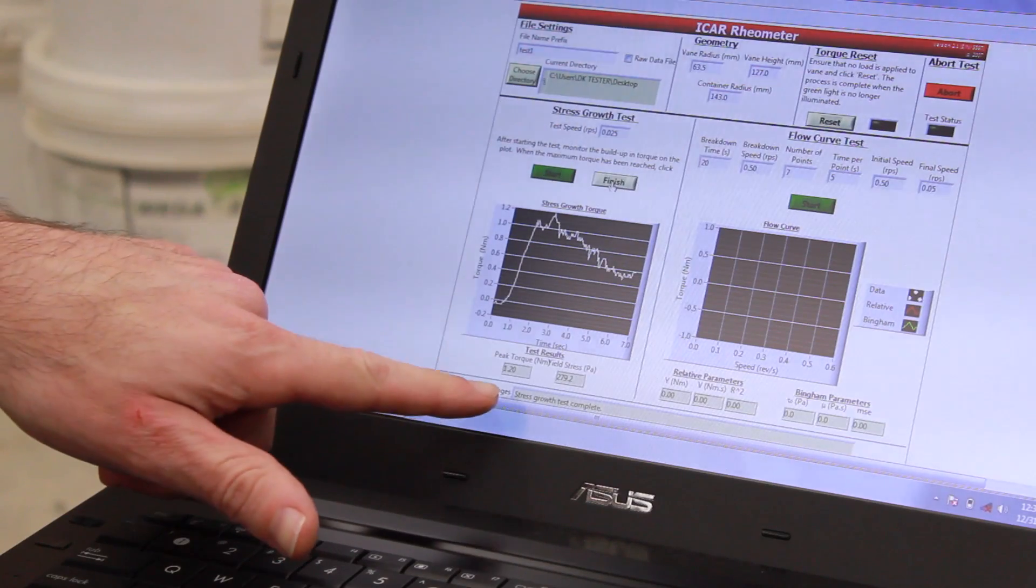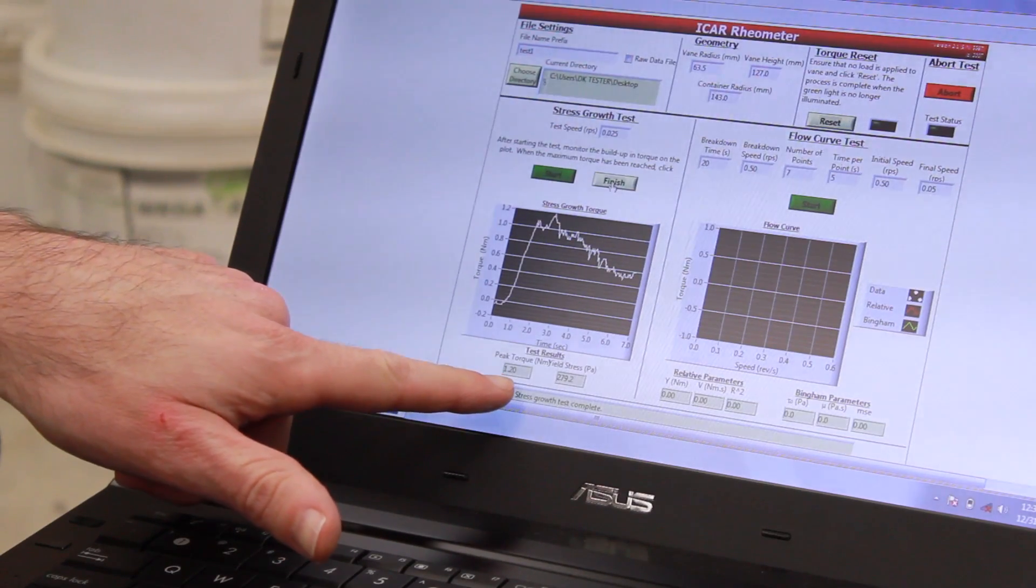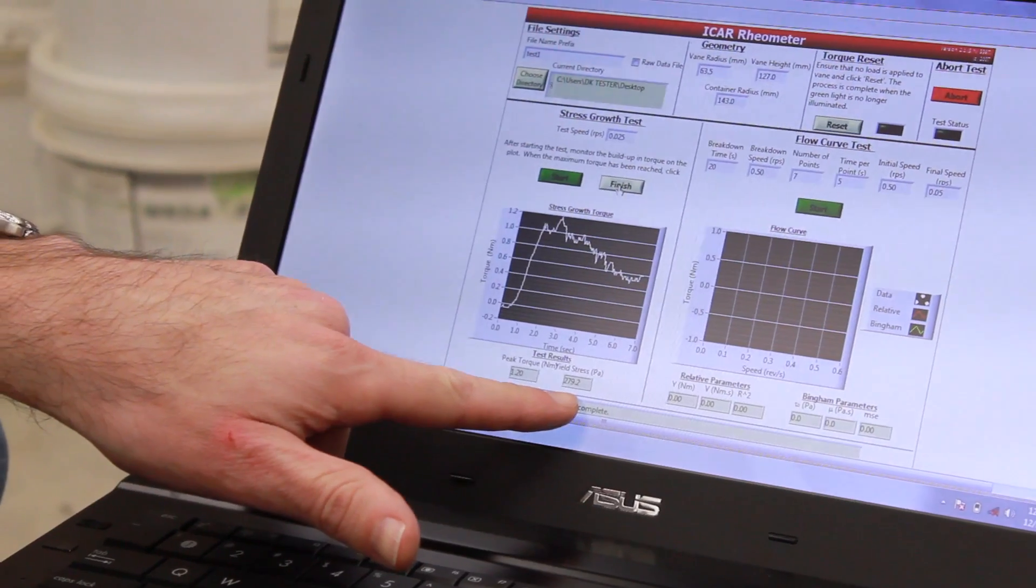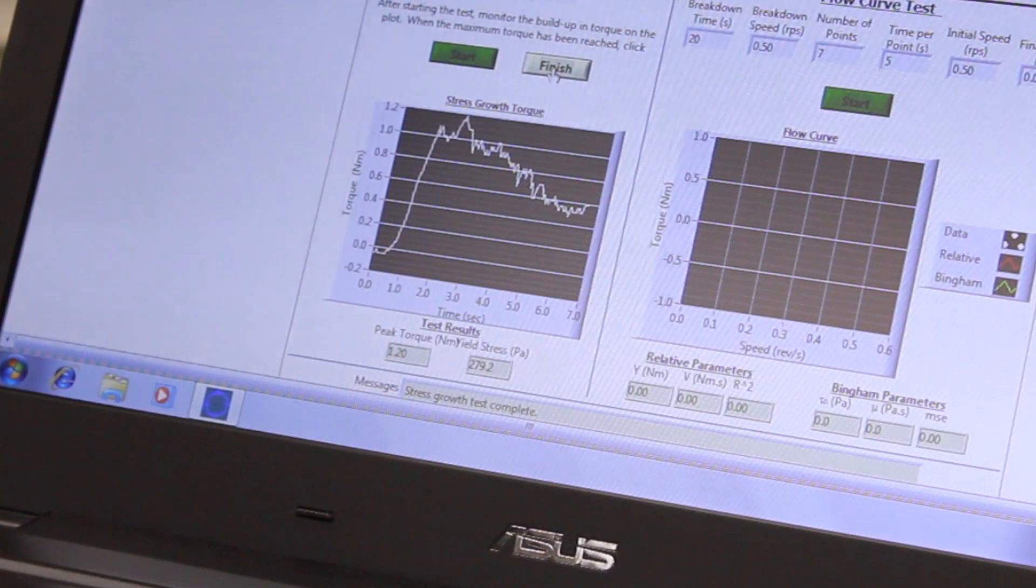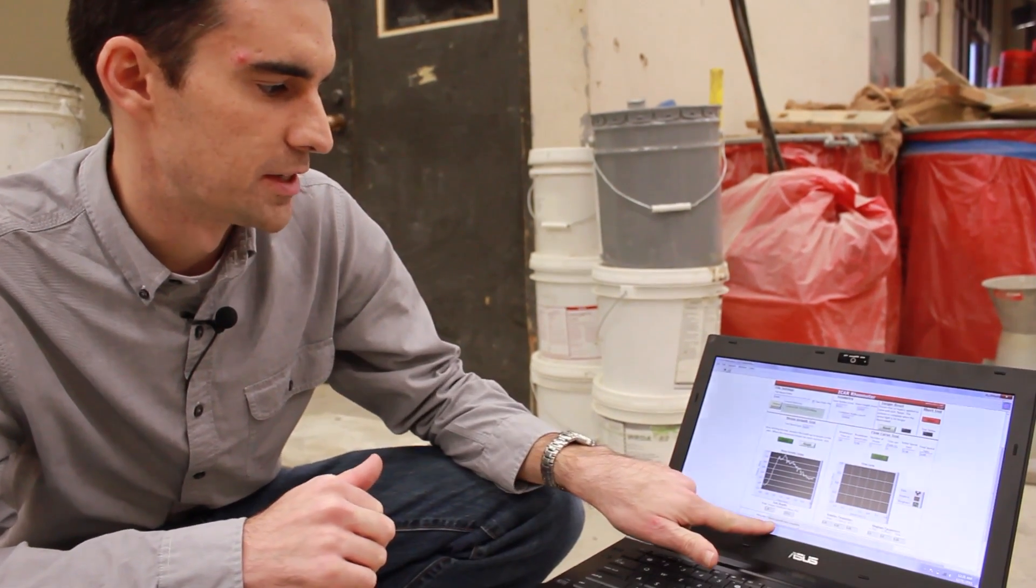And so now after the test is finished, we see the maximum torque and the static yield stress of 279 Pascals. And we see down here the message at the bottom, our stress growth test is complete.